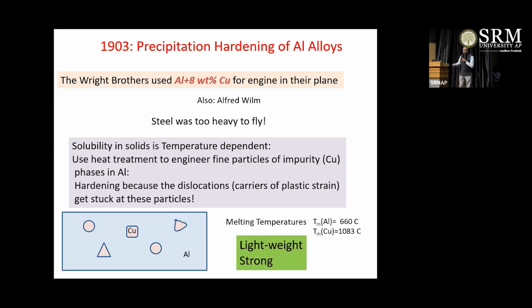So if I take a liquid mixture of aluminum and copper and cool it down, the first of the two which will freeze is copper, and it forms these little particles in the matrix of aluminum, which will freeze at a lower temperature of 660 degrees centigrade. So what happens? This is a very interesting concept called precipitation hardening. And that leads to formation of a material which is light like aluminum, but it is very tough because the carriers of mechanical deformation, dislocations, get stuck at the interface between these two materials. And that's what was very important for the development of the aeroplane by the Wright brothers.